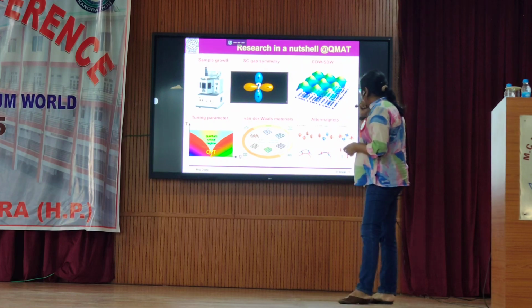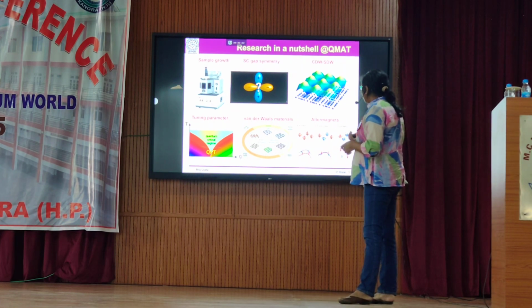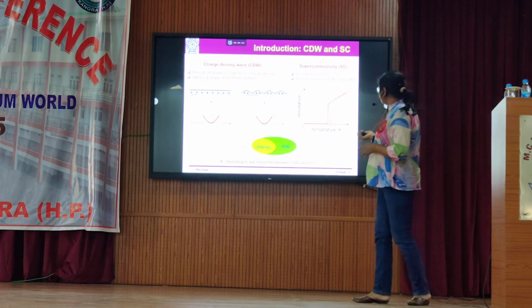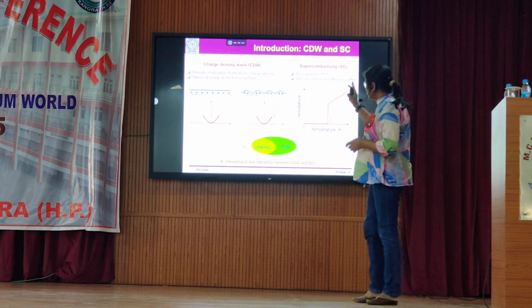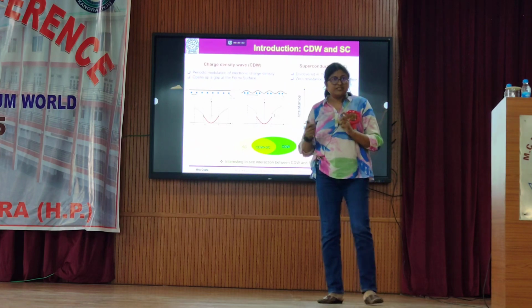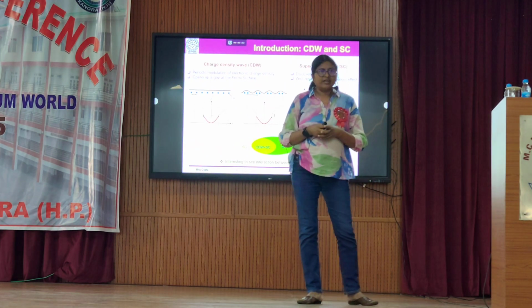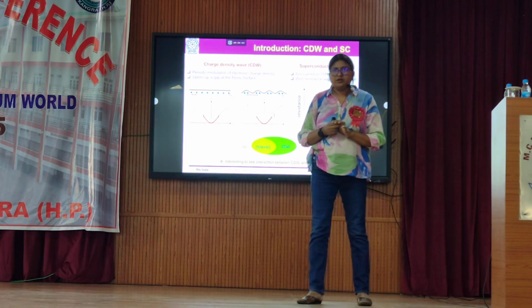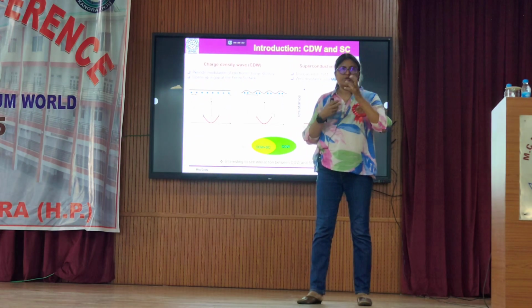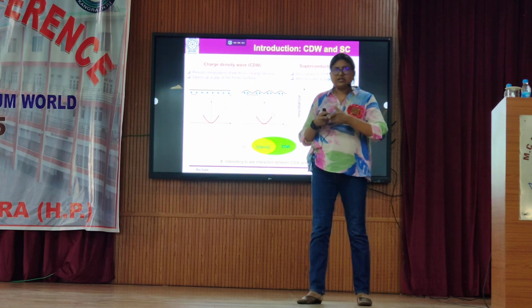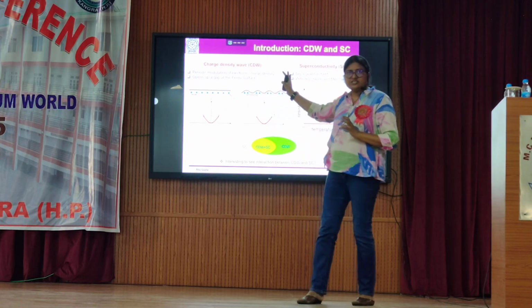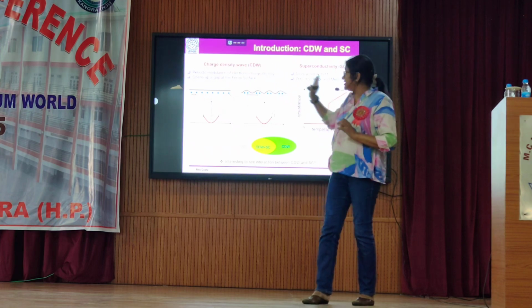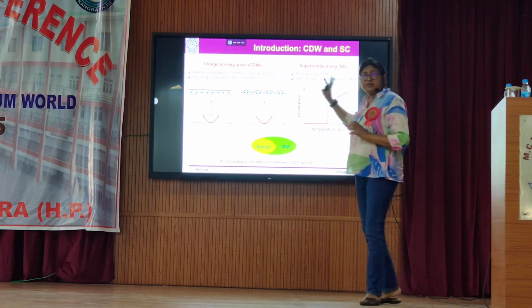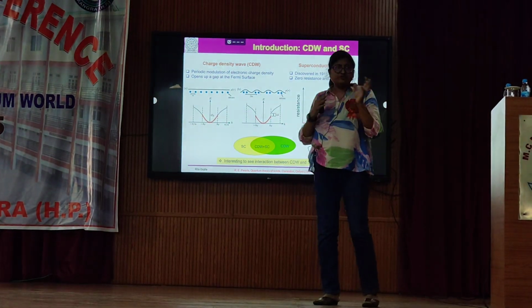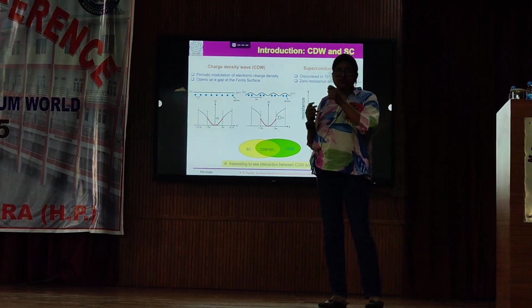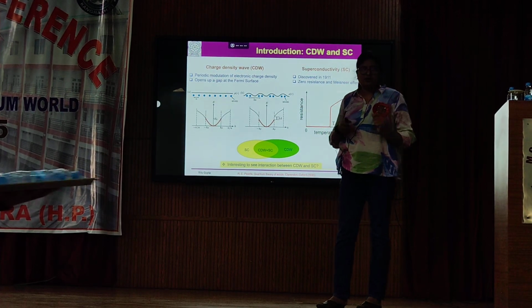Okay, so these are some of the fields I am looking at. I just want to mention the charge density wave. This is a phenomenon which competes with superconductivity. In many materials where you see a very high superconducting transition, that transition was achieved once this charge density wave was suppressed. Okay, so what is the charge density wave? As the name suggests, there is a density of charges. It's not that the charges are uniform, but they are periodically modulated.